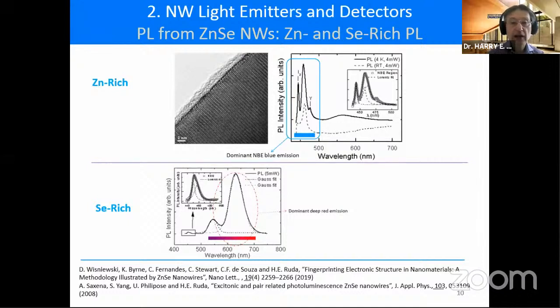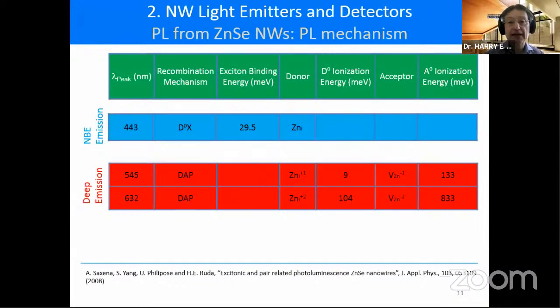So if we want to make a laser that's one color or a laser that's another, we can do that, because this is luminescence. Obviously, this is radiative recombination, so this is light being given off on excitation of this material. When we grow under zinc-rich conditions, a zinc to selenium ratio greater than 1, typically 5 in this case, we're dominated by band edge luminescence. 470 is the band gap, and you can see donor-bound exciton emission near the band edge. On the other hand, if we were to adjust the same ratio back to selenium to zinc, 5 to 1, we'd end up with dominant radiative deep level emission, which is this red band shown at the bottom of the figure. And the blue band, which I showed you earlier, has been quenched. The two peaks in the red band are due to donor-acceptor pair recombination, and this is in fact due to native defects in the material.